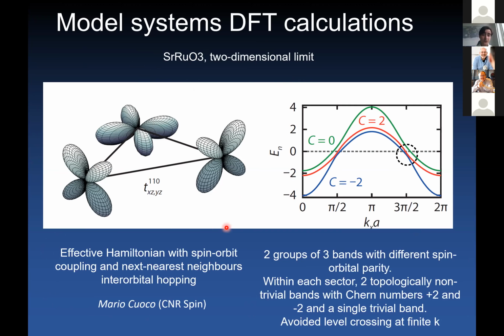So the novelty of the calculations of Mario and colleagues was that they included in their effective Hamiltonian both spin-orbit coupling and next nearest neighbors interorbital hopping. And this has allowed us to show that the system actually possesses topologically non-trivial bands in the two-dimensional limit. So this Weyl system, that is present in 3 dimensions, when you go to 2D, it displays 2 topologically non-trivial bands with Chern numbers +2 and -2. So these are prevalently dyz and dxz orbitals, and the dxy orbitals instead are topologically trivial.